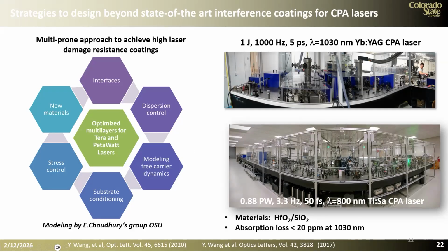This is especially necessary for the Aleph laser. And also substrate conditioning. All of these come into play in designing coatings for these lasers. The typical materials that we use right now are hafnia and silica, and we can make coatings that will have a very low absorption loss at 1030 nanometers. But it turns out that absorption loss, when you have picoseconds or femtoseconds, is not the dominant parameter. It is a dominant parameter when we have nanosecond pulse duration.